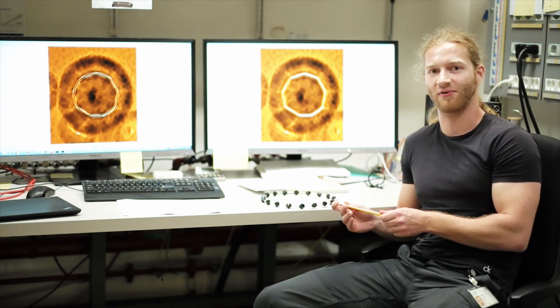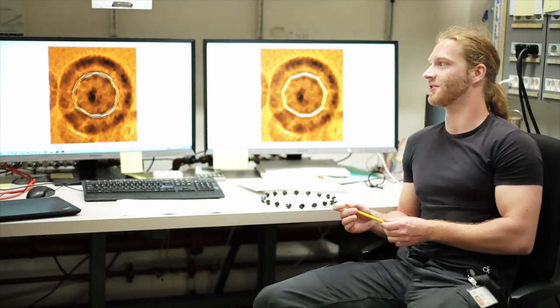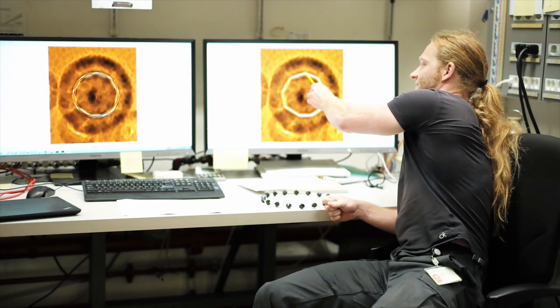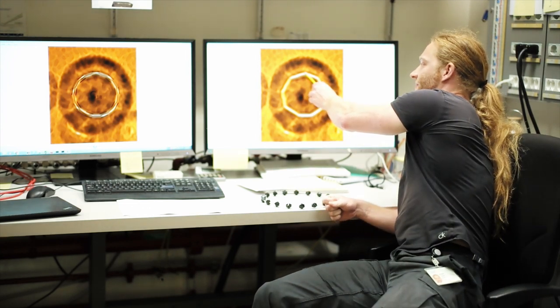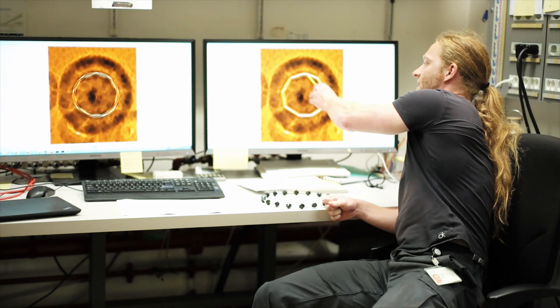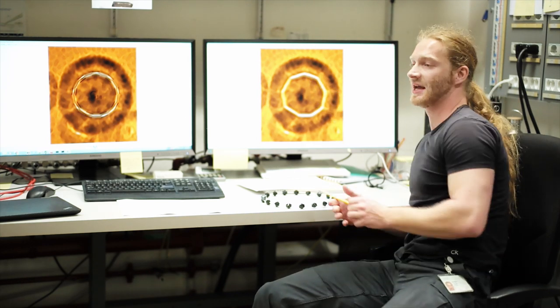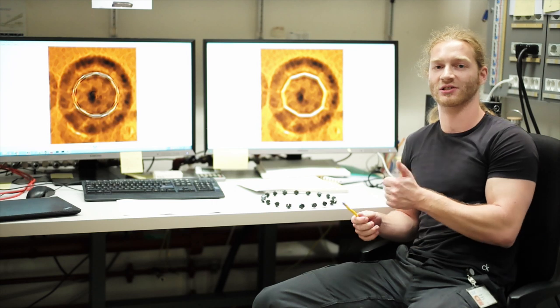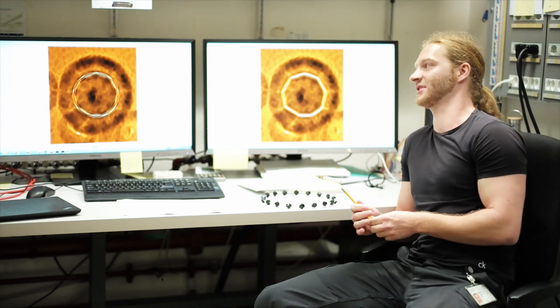And based on these atomic force microscopy simulations, we could clearly determine that the kind of contrast that we saw in the atomic force microscope experimentally, so this nine-fold symmetry, the nonagon, clearly corresponds to the structure of the triple bonds and the single bonds. In particular, we could see from our simulations that the positions of the corners are the positions of the triple bonds, and the edges of the nonagon are the single bonds. So in this way, we could really clearly identify what the actual structure of the molecule is.